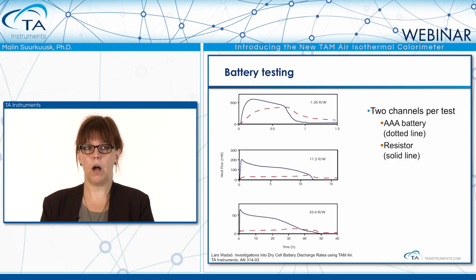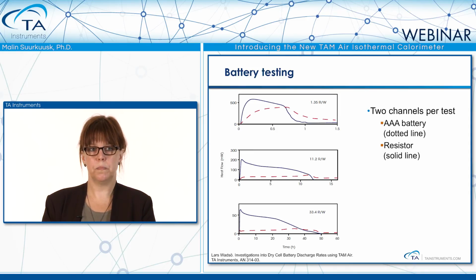In the first top graph, we have a very low resistance connected to the battery, and we can see that the heat produced both in the resistor and in the battery is quite high, and the battery drains very fast. So this is 1 hour before the battery power goes down. And in the bottom graph, we have a much higher resistance, and we can see that the battery power lasts much longer, and there is not much heat produced either from the battery or the resistor that we are measuring. And that could last for then 40-50 hours with this resistance.